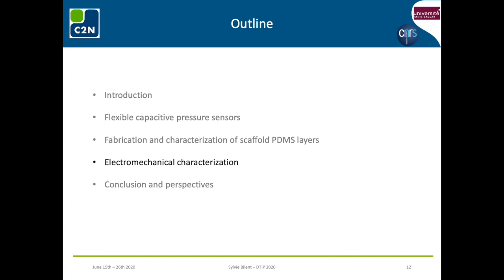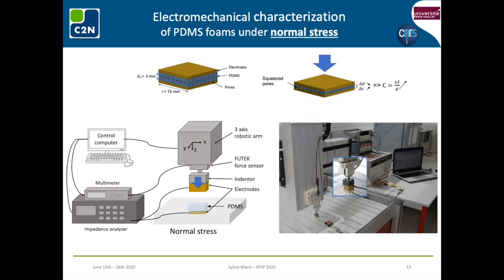Let us move to the electromechanical characterization of sensors fabricated with the designed PDMS scaffolds used as deformable dielectric layers. To do this, we use an electromechanical characterization bench composed of a 3-axis robot which applies force to the pressure sensors under test. A commercial force sensor monitors the force actually applied through an indenter to the tested sample. The variation of the capacitance induced by the sensor compression is recorded through an impedance analyzer connected to the electrodes placed on each side of the PDMS scaffold. The capacitance change under stress is due to the reduction of the distance between electrodes as well as to the increase of the permittivity of the squeezed scaffold PDMS layer.